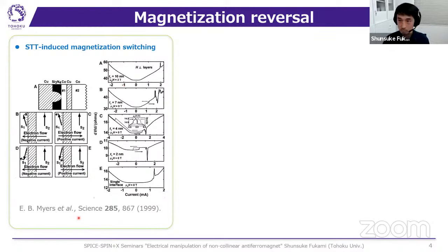As most of you know, the current can induce magnetization reversal. This was first observed by Cornell's team in 1999: spin transfer torque induced magnetization switching. They used CPP GMR structures, cobalt, copper, cobalt, passed current through this GMR device, and observed bidirectional magnetization switching, as shown here. This can clearly be used for non-volatile memory devices, and tremendous effort has been devoted to realizing a non-volatile device.